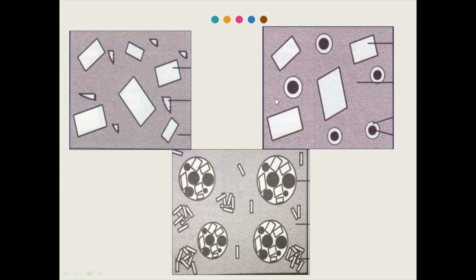Now the gamma 1 matrix is common to all. The only addition is gamma 2, and that too in low copper, because it forms in that reaction. Because in high copper, in both admixed and unicomposition, there is elimination of the gamma 2 phase, so there is no gamma 2 phase at all in the matrix.